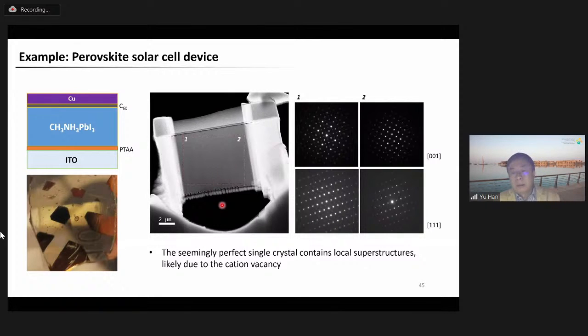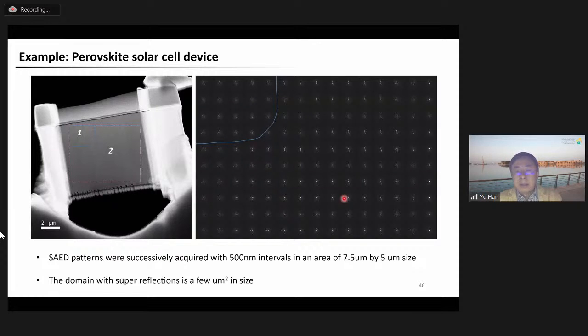And this is the slice we prepared, extracted from this device. And very interestingly, we found that when we characterized this active layer of the solar cell using electron diffraction, there are superstructure reflections observed in some local areas. Okay, so again, it's from a single crystal, but the structure is not uniform throughout the crystal. At some local areas, we can observe the superstructure reflections in the electron diffraction pattern. And then we performed a more careful study, collecting electron diffraction patterns in a systematic manner throughout the entire specimen. Okay, and then we found that the superstructure is concentrated at this area, and the domain of the superstructure is about a few square microns in size.